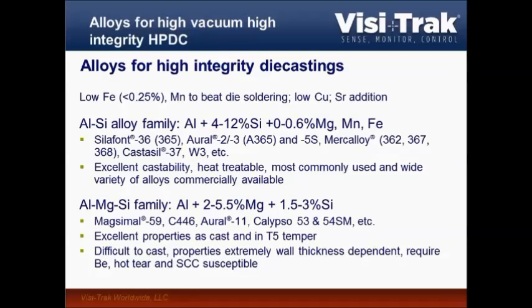The other, more problematic alloy family is aluminum plus some magnesium plus a little bit of silicon. The most famous candidate here is Magsimal-59. I heard it's actually not easy to get that alloy in North America, and it's becoming less and less popular even in Europe. It was developed because it has really excellent properties as cast or in a T5, so just an artificial aging temper, but it's very difficult to cast, and really it just eats your dies.